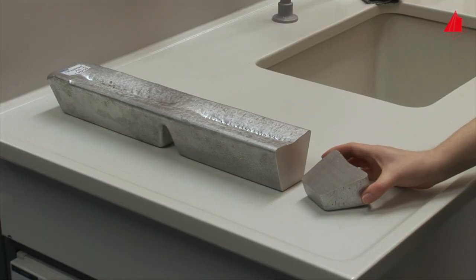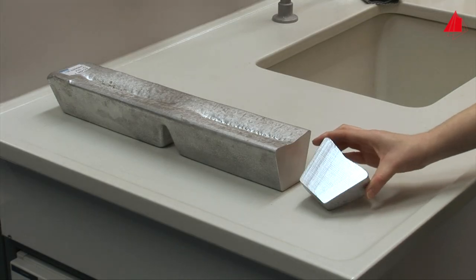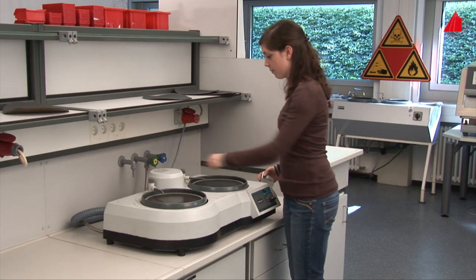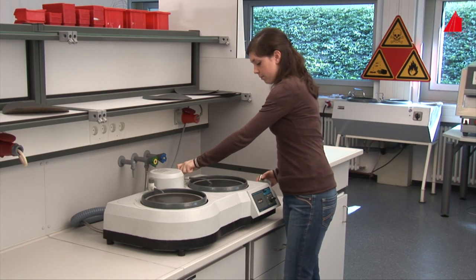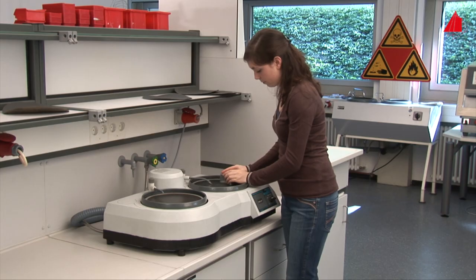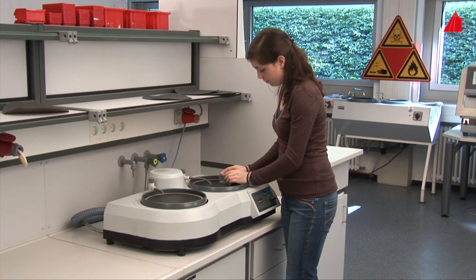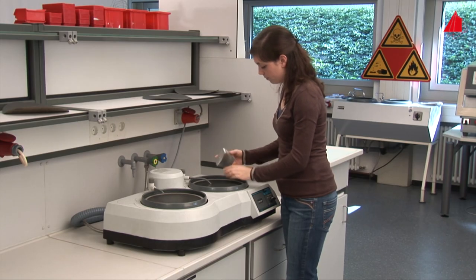Back into the lab, not much is to be seen on the cross section apart from the typical saw marks. In the next step, the material tester removes the saw marks by careful wet grinding with silicon carbide paper. On the one hand, this serves to produce a flat surface. On the other hand, the plastic deformations are removed that were generated by sawing. After the first grinding operation with coarse grained paper,